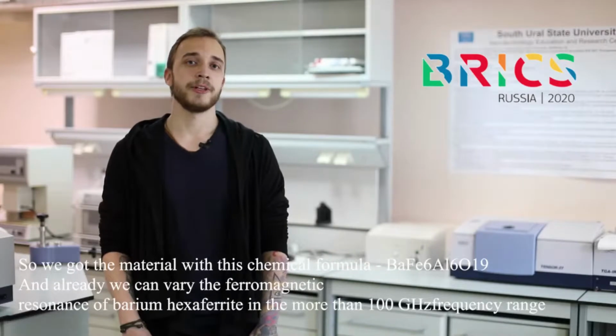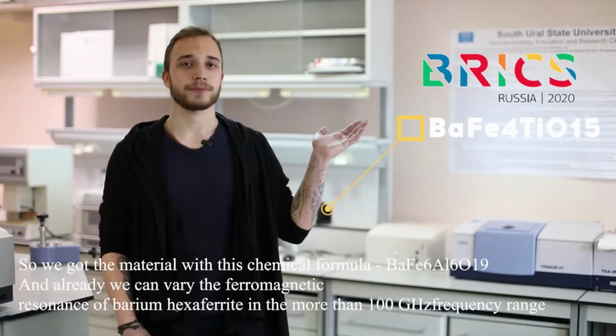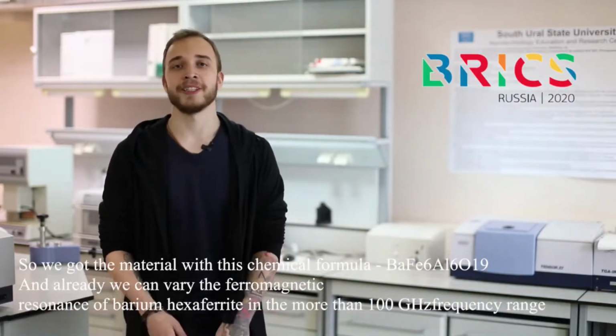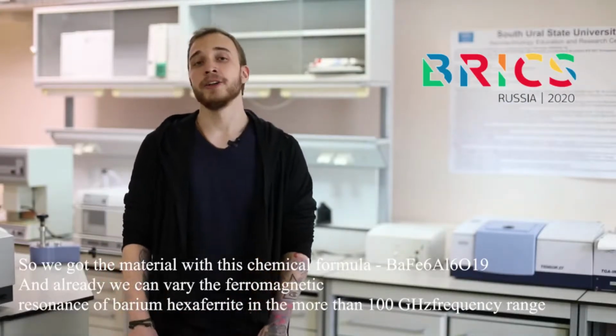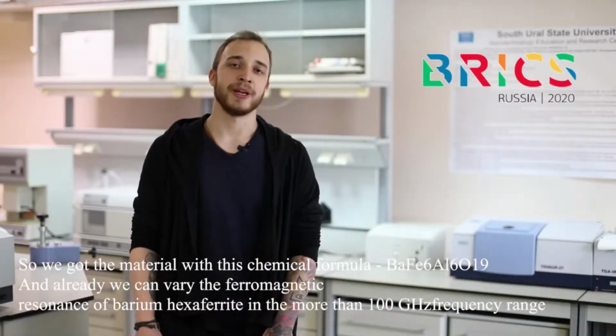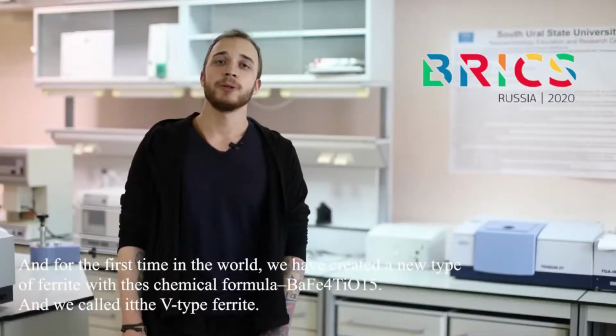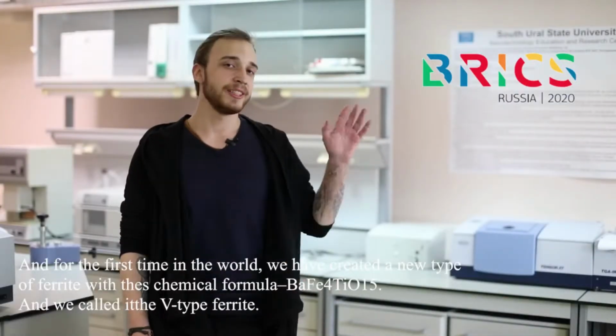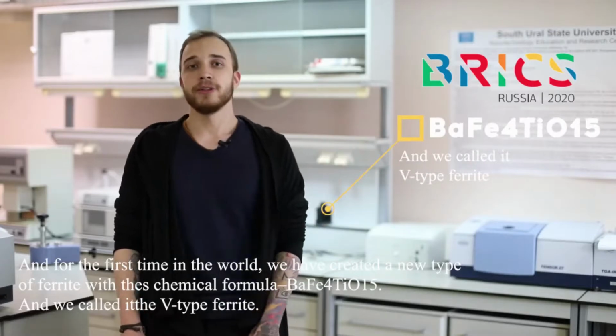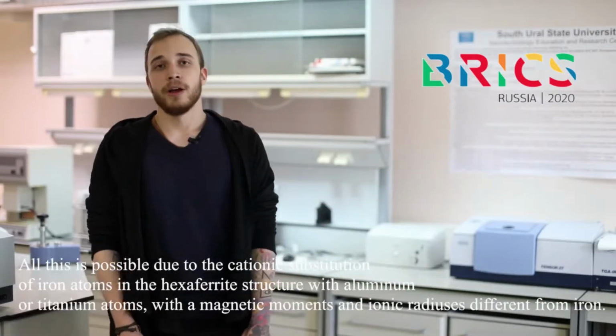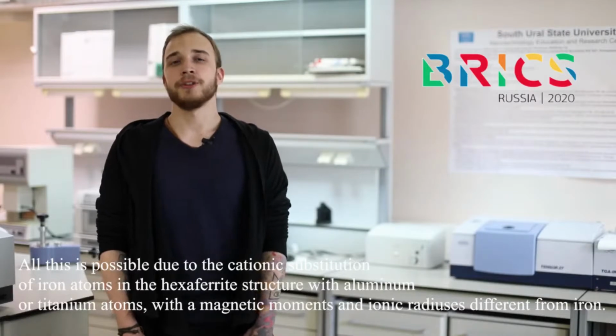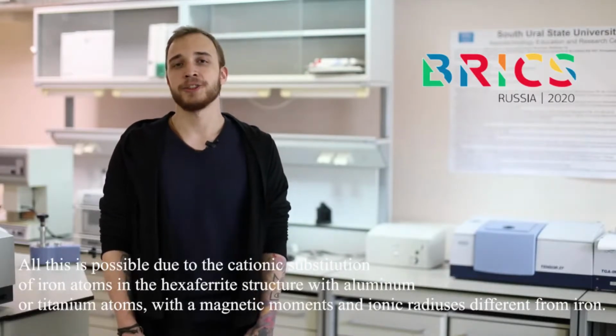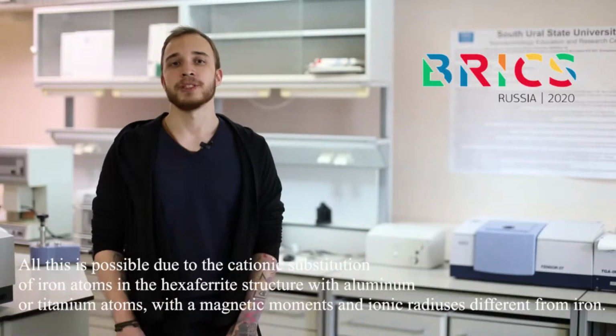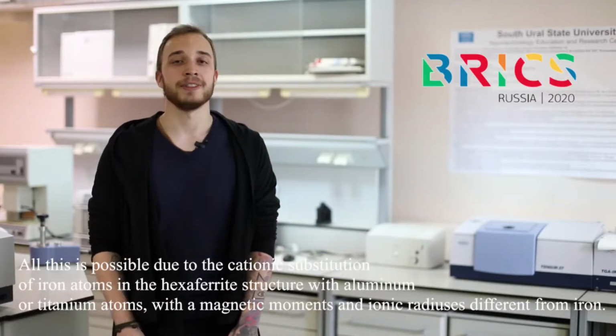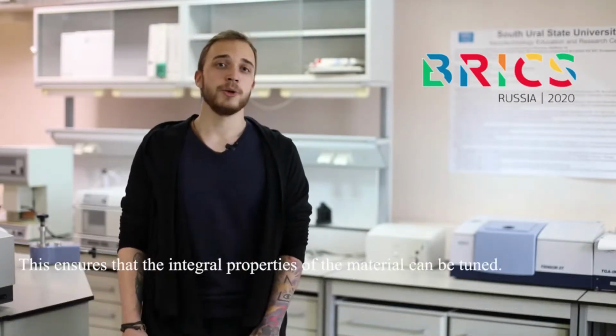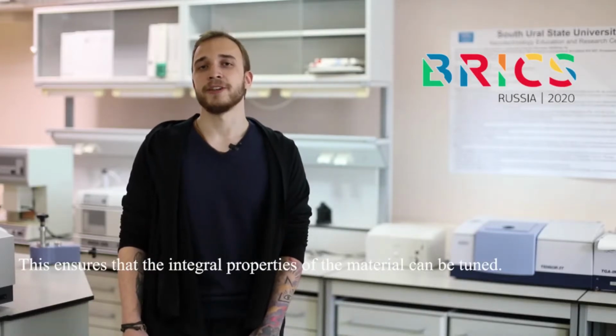So we've got the material with this chemical formula. And already we can vary the ferromagnetic resonance of barium hexaferrite in the more than 100 GHz frequency range. And for the first time in the world, we have created a new type of ferrite with this chemical formula. And we call it the V-type ferrite. All this is possible due to cationic substitution of iron atoms in the hexaferrite structure with aluminum or titanium atoms, with magnetic moments and ionic radii different from iron. This ensures that the integral properties of the material can be tuned.